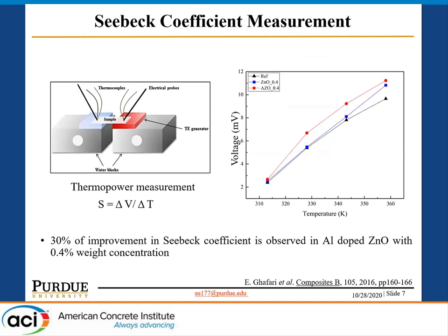This slide shows how we performed the Seebeck measurement. For the Seebeck measurement, the thermopower is calculated as the difference of the voltage divided by the difference of the temperature. On your left-hand side is temperature versus voltage output. We have the reference sample and two other samples with zinc oxide and aluminum-doped zinc oxide. We found that a 30% improvement in the Seebeck coefficient is observed in aluminum-doped zinc oxide with 0.4 weight concentration.